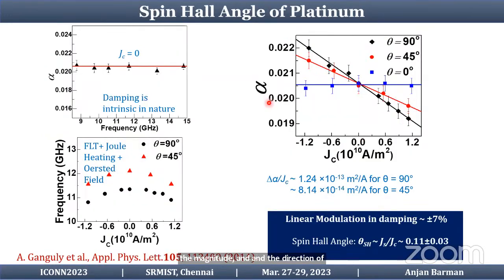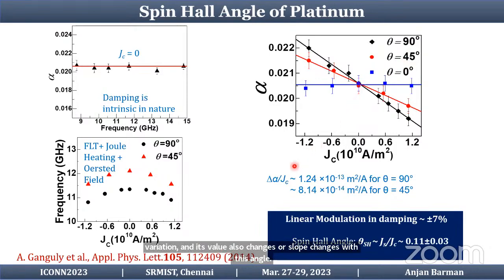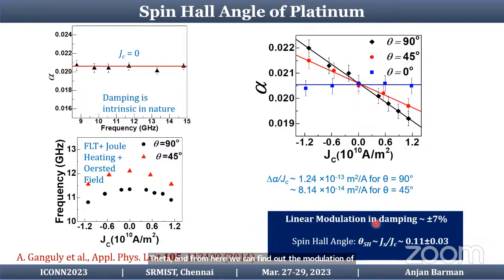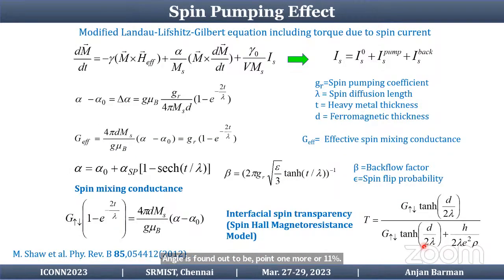Here is the result, where you can see alpha as a function of charge current, which shows an asymmetric variation, and its value, or slope, also changes with this angle theta. From here, we find the modulation of damping to be plus minus 7% for cobalt platinum, or sorry, it's permalloy platinum, and the spin Hall angle is found to be 0.11 or 11% spin to charge conversion.